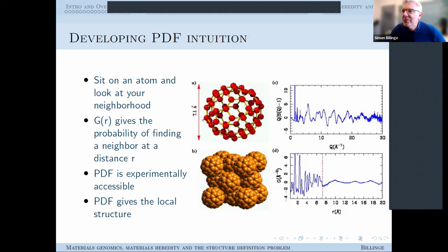I can do a double sum over every atom in this C60 molecule, and I can find where all of the interatomic distances are, and I can make a histogram, and this is a histogram. And the longest distance in C60 is across the diameter from this guy to this guy, for example. And it's a 7 angstrom ball. And so the last sharp peak is at 7 here. That's a 6 and that's an 8. So this is 7.